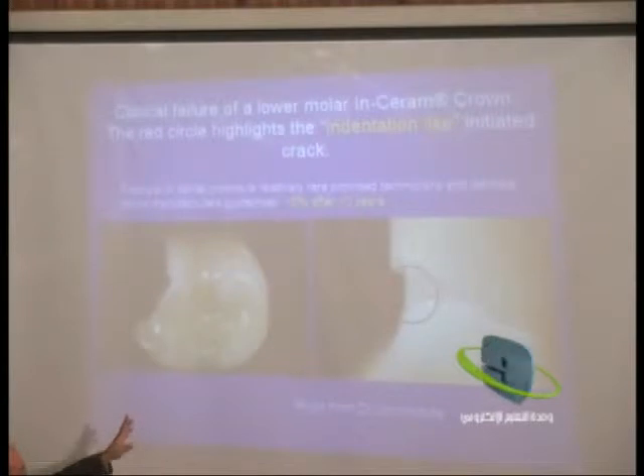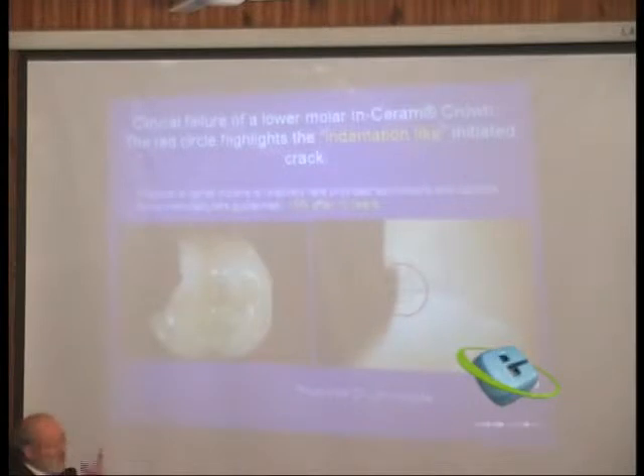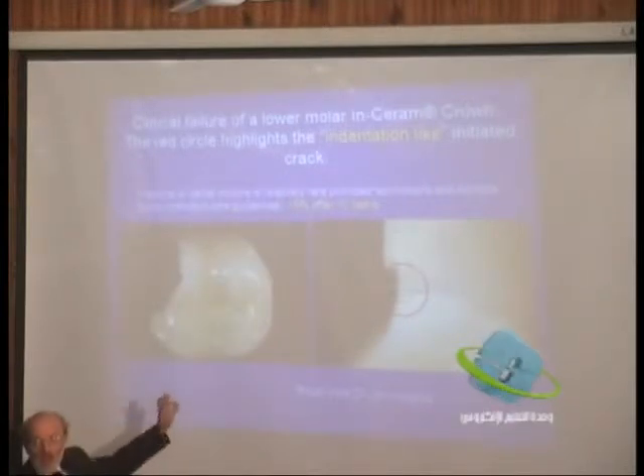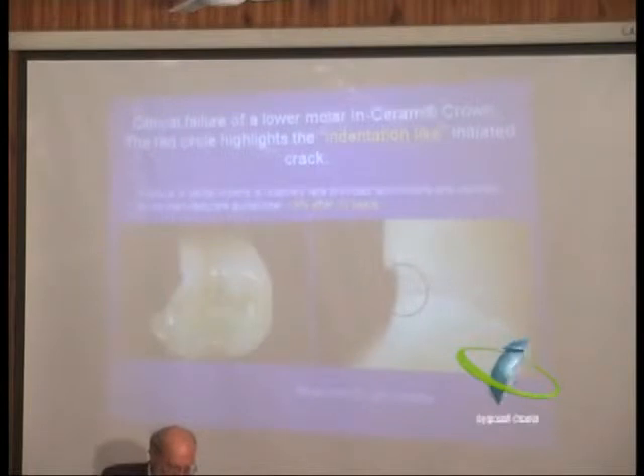Another former student, Jim Ironside, again, this is a failure of an Inceram system. And he saw this chipping process or cracking problem, and again, he was able to extract that crown afterwards and look at it. Sorry, I must have thrown that other part away. But he had to blame himself as a prosthodontist. He had made the coping material too thin, and there was a gap underneath it, so this was the origin of why this system failed.